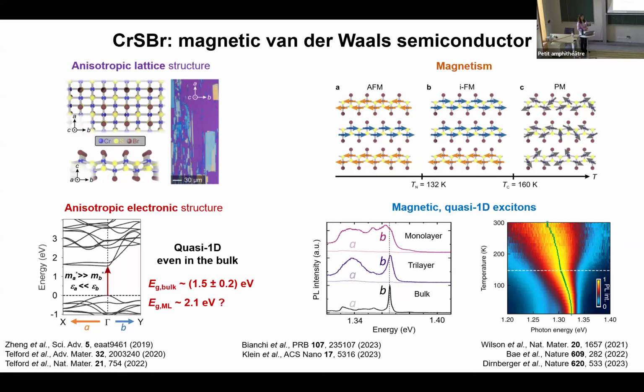When we follow this exciton emission as a function of temperature, that is, as a function of the magnetic environment surrounding these excitons, we see an exciton emission that gradually broadens, however shows a kink at the Néel temperature and dramatically broadens above the Néel temperature. So it shows that excitons in chromium sulfide bromide must be highly coupled to the magnetic order. So there is a lot of high-profile research dedicated to understanding or manipulating magnetism in chromium sulfide bromide.